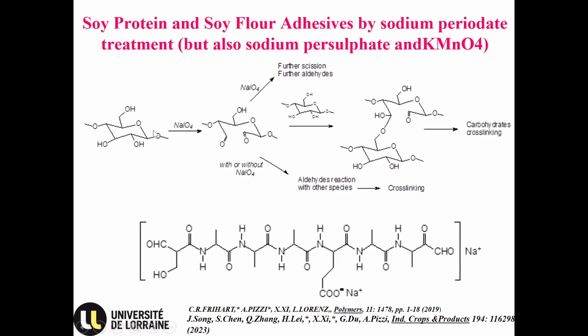If you take a carbohydrate and you treat it with sodium periodate, what you do is cut the carbon to carbon bond and you form two aldehyde groups. Two aldehyde groups can go to carbohydrate cross-linking itself, or the aldehyde can react with other species to form cross-linking. And also the protein itself, the protein is cut and produces aldehyde groups.